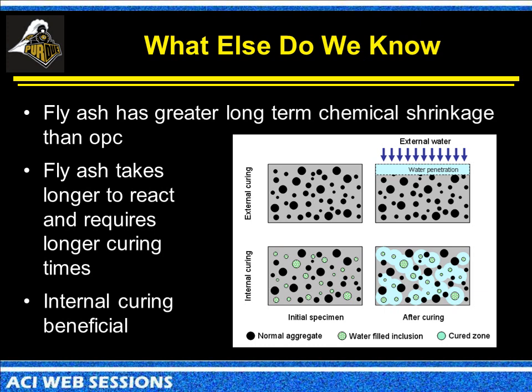So you're putting a bigger driver on this autogenous shrinkage that's taking place inside the system. So we have greater chemical shrinkage when we've got fly ash. We also know that the fly ash is going to take longer to react, and we have a lot of discussion about what do we need in terms of curing requirements. We also know that if we go with more dense systems, it's harder for us to get that external water. Even if we do get it on the surface, it's harder for us to get that inside of the concrete.